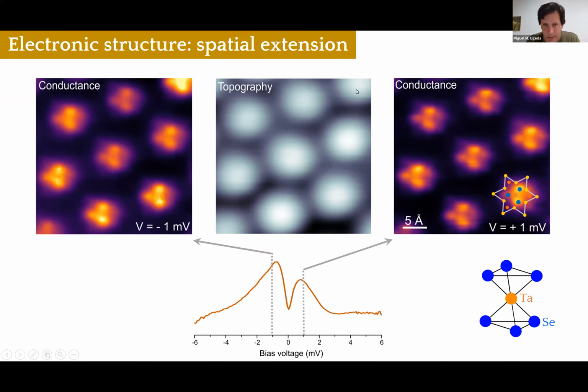In particular, in this region where you see some Stars of David, we have done conductance maps at -1 milli-electron volt and plus 1 milli-electron volt. You can see that in both cases the conductance is pretty much identical. So the intensity of the conductance is mostly focused on a triangular shape with some secondary spots here, which reflect these three selenium atoms, which means that these two states are located at the central atom of the Star of David.